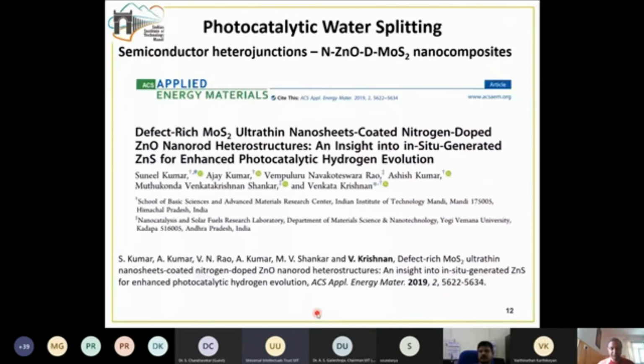In yet another work, we thought it's better to use molybdenum disulfide, because MoS2 has a lot of exposed sulfur atoms, and these exposed sulfur atoms have a strong affinity towards H+ ions in the solution. Then we thought, can we purposely introduce more and more of these exposed sulfur atoms? So we created a defect-rich MoS2, which means that there are more dangling sulfur bonds in that MoS2. And then we made a composite of this defect-rich MoS2 with zinc oxide nanorods in order to prepare heterostructures. These heterostructures were used for photocatalytic hydrogen evolution under direct sunlight radiation. And this gave a much better result. This work was published in ACS Applied Energy Materials in 2019, and was also done by my PhD scholar, Dr. Sunil Kumar.